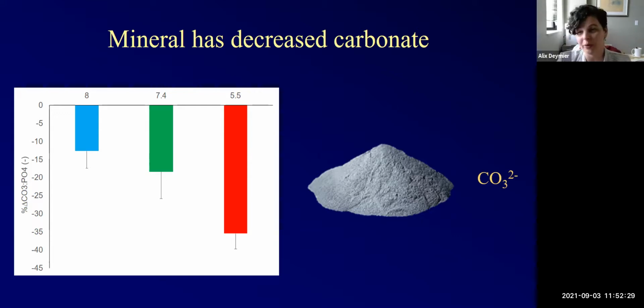So doing whole bone analyses and isolating them, we do X-ray diffraction on whole bone, which also just gives us crystal information. So doing whole bone measurements with techniques that don't require you to take out the collagen, that's how we get the composition. So Raman, FTIR, X-ray diffraction can essentially allow us to get information while ignoring the collagen.